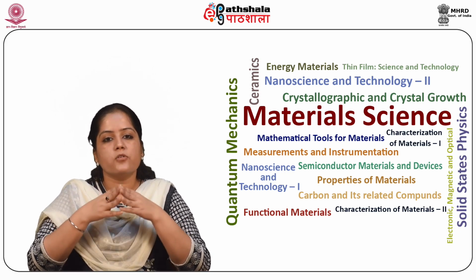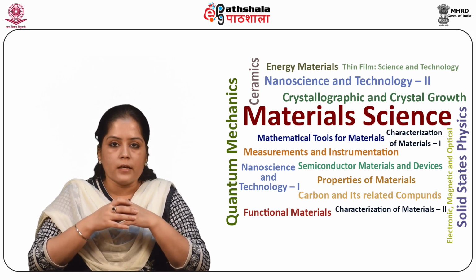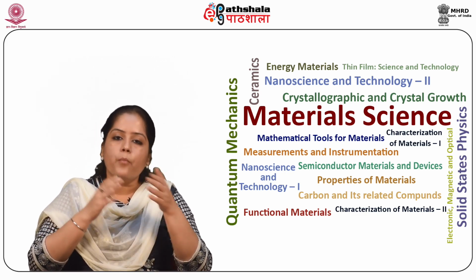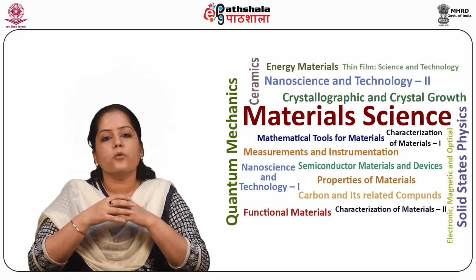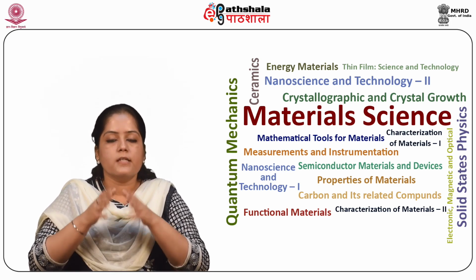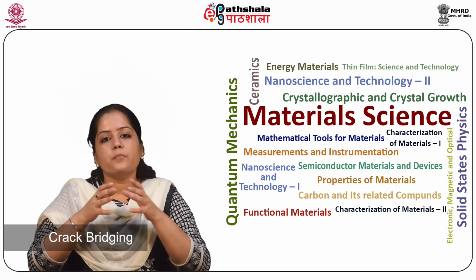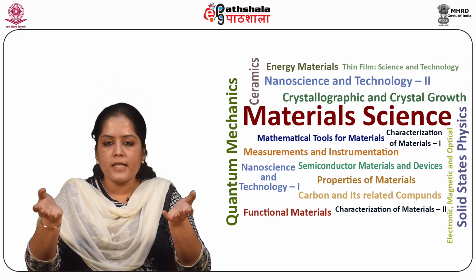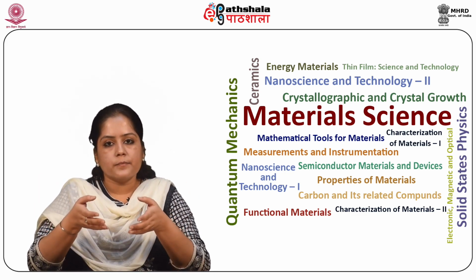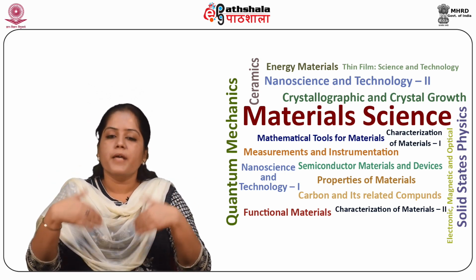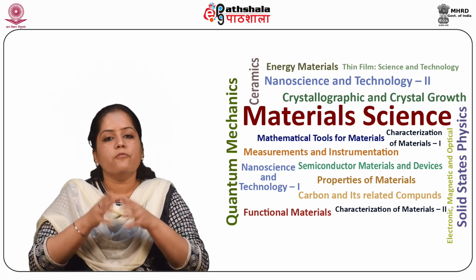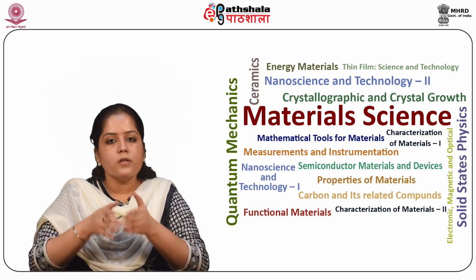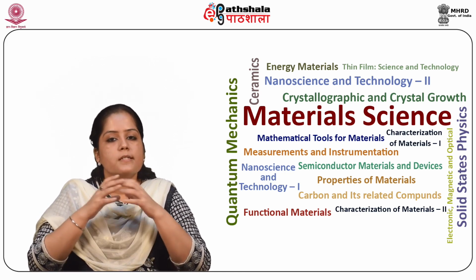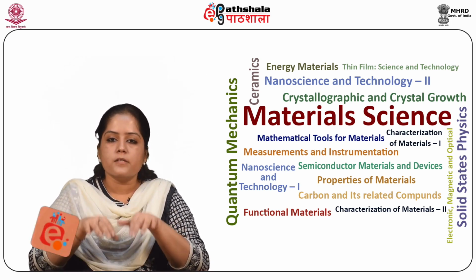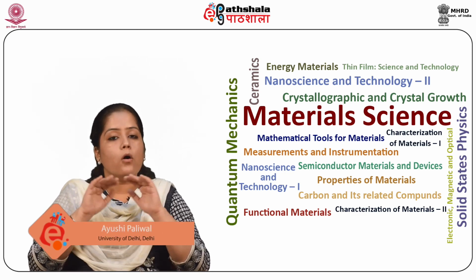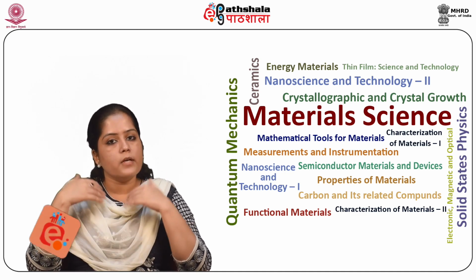An example of stress-induced phase transformation is transformation toughening in zirconia and other ceramics. Both the stress-induced transformation and micro-cracking lead to a very significant increase in the fracture toughness. Now, crack bridging. It is often observed in large grain-sized ceramics. Some large grains bridge the two crack surfaces behind the crack tip. More than one grain may form frictional interlocking bridges across the two crack surfaces. These bridges take up part of the load on the crack tip and thus reduce the effective stress intensity on the crack tip. The measured toughness is therefore increased.